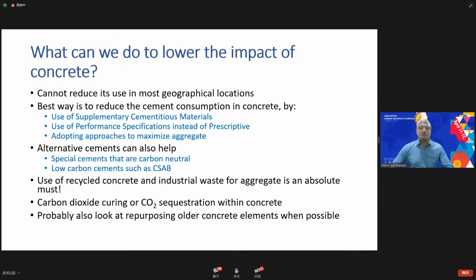Carbon dioxide curing or CO2 sequestration within concrete is an option that has been suggested. There are limitations with respect to the chemistry, but there are strategies which can enhance this by capturing the amount of CO2 inside concrete and utilizing it for curing the concrete instead of water.